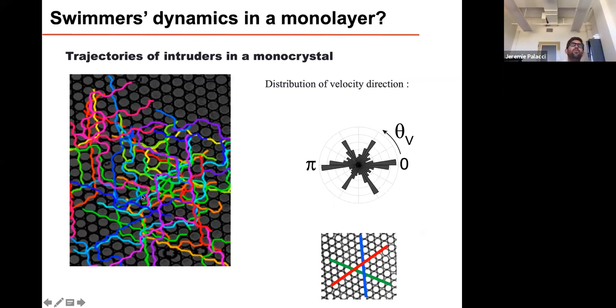A simple argument for that is that it is much easier to unzip a crystal than to actually push head first, which would generate a full disinclination, which just requires too much energy. Something I didn't say so far is that the surface density in the experiment is 0.68. So it's a crystalline monolayer, but it's not super dense. There's still a little bit of room to reorganize.